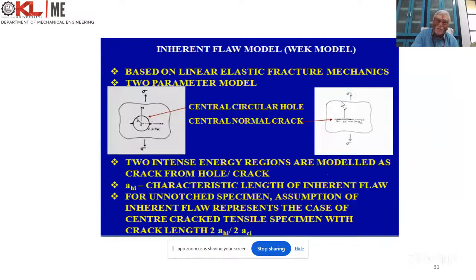What is the meaning of the inherent flaw model? It means that wherever there is a cutout, there is a chance of stress rise. From that inherent flaw, one crack will be generated there only, it will propagate and fail. If you are able to understand that zone, then your prediction will be close to exact. It demands test data. From the test data, you superimpose and get the inherent flaw size, then apply that flaw size to other components.